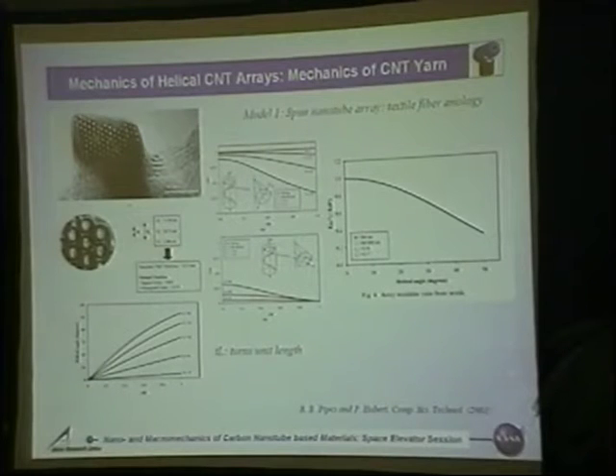So even if for the pure material you had like 100 gigapascal, so these are the scales. Even at the nano scale, you have not increased from nano to the meso to the micro scale, but even at the nano scale you have degraded the modulus by about 60%. So that 60% of 100 gigapascal means it comes down to about 40 gigapascal. It's not too bad, but it's still degrading. But that is degrading at the nanoscale.